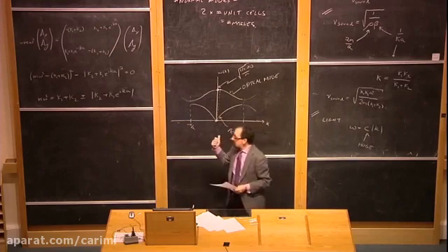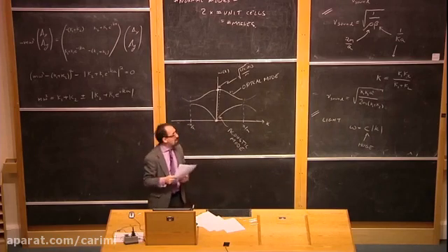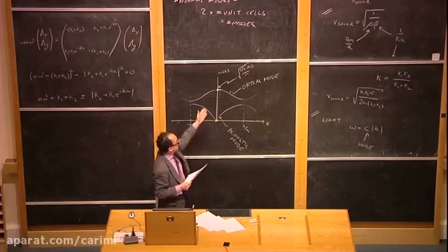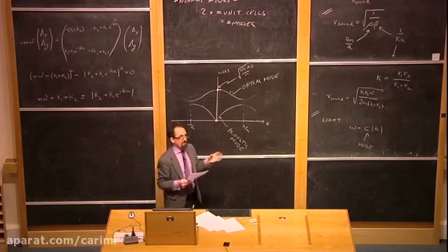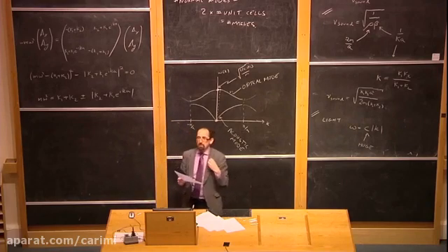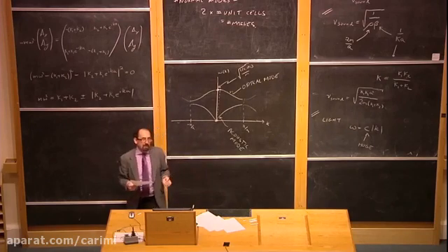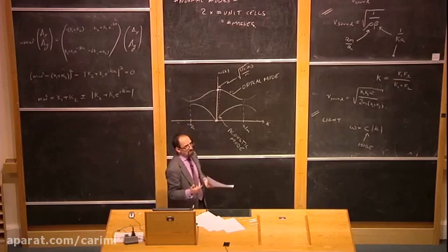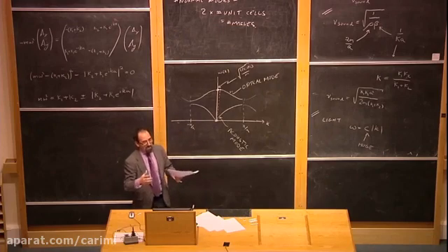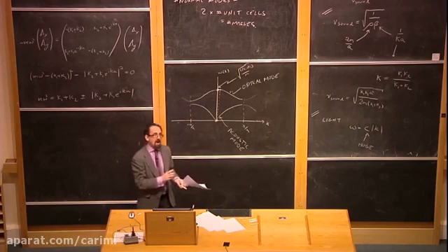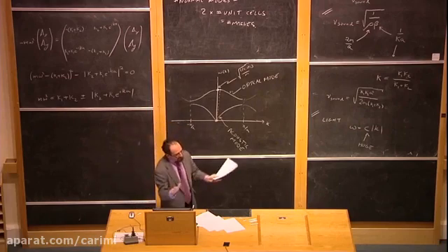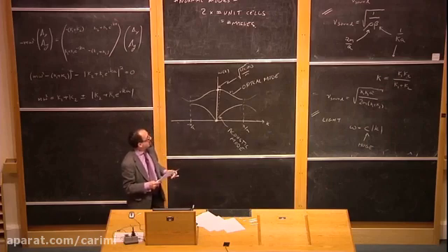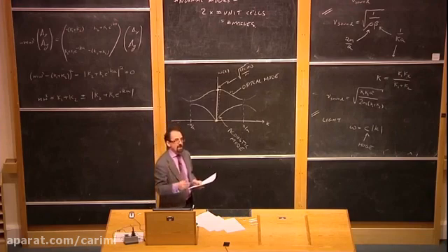Now, so that's the nomenclature of why people call this the optical mode. Whenever you have interactions with light and vibrations, it's inevitably the optical mode. But I should be a little bit honest: the process I described to you, by which you absorb a photon and you emit a phonon, actually does not occur. And the reason it doesn't occur is because there's a conserved quantum number, the spin of the photon. Photons have spin, phonons do not. So if that process were to occur, you would violate angular momentum conservation. That's definitely bad. You don't want to violate angular momentum conservation. So in fact, no such process exists by which a single photon is absorbed and a single phonon is created.